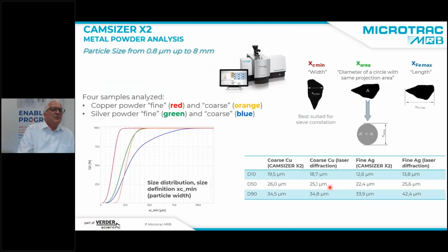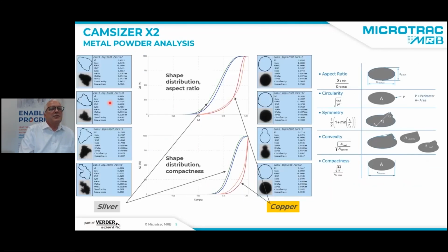As an example, we show here four samples, 2 copper and 2 silver particles. The powder is either fine or coarse, and you see all the particle size, and here is shown the minimum dimension, the minimum width. There is not a real difference seen, even when you compare all the sizes at D10, D50, or D90, either with a CAMSIZER X2 or even with a laser diffraction, for example. They are very similar. So we don't see much difference, but there are big differences, as we can see here in these pictures. The silver particles are quite fringed, while the copper particles are spherical. And how can we check these?